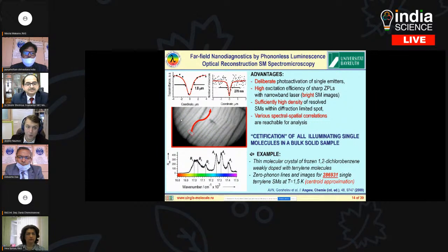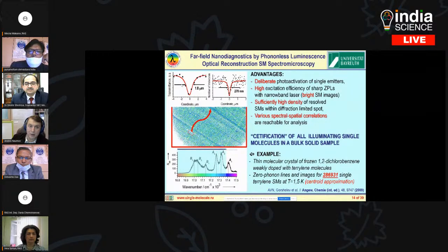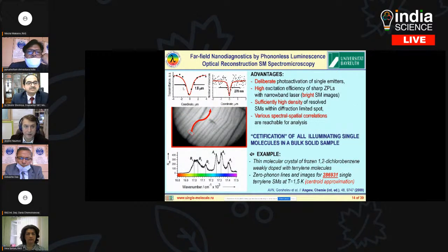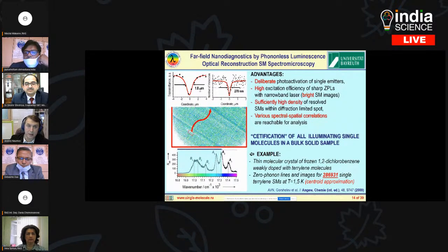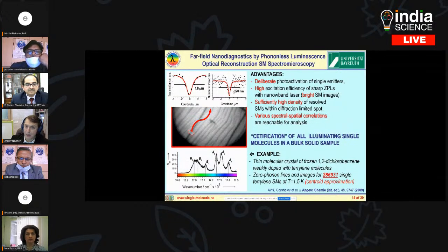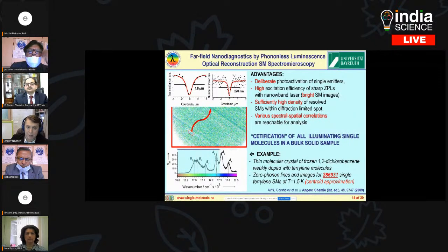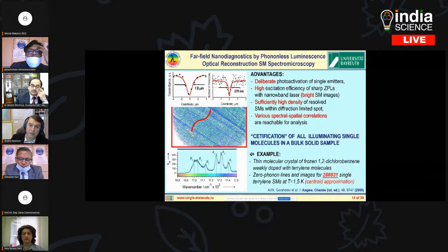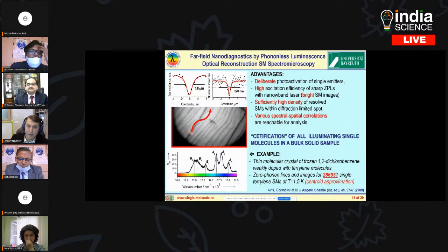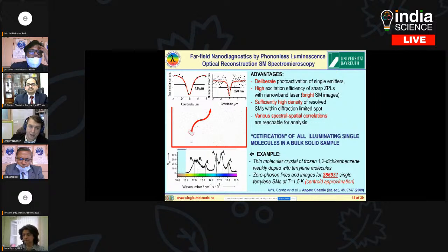And you see, in a usual white light microscope, of course, I'm limited by the diffraction limit. I cannot reconstruct the shape of the crack. You see here, it's just 1.8 micrometers. But if I reconstruct the spatial density of my label molecules, I'm now not limited by the diffraction limit, because for each label molecule, I reconstruct the position with nanometer accuracy, so I can recalculate the shape of the crack, of this defect in my sample.